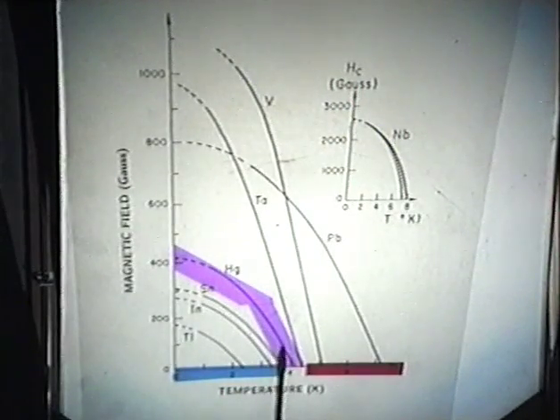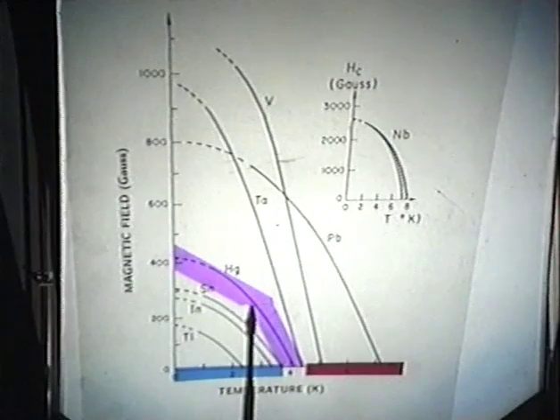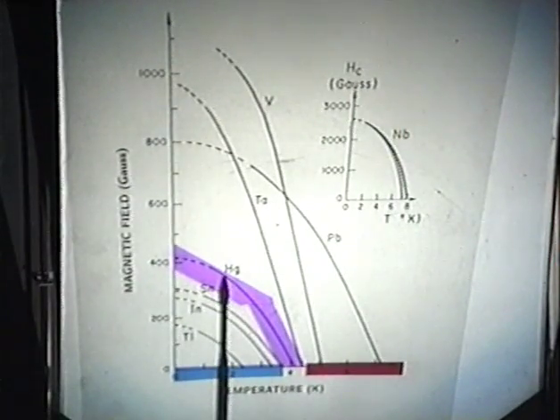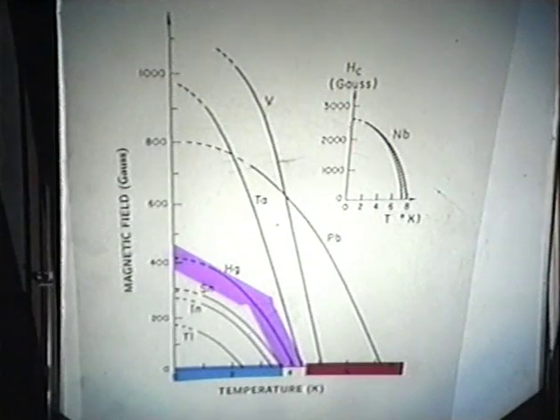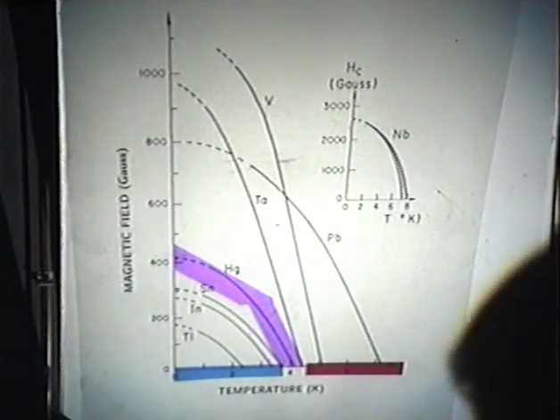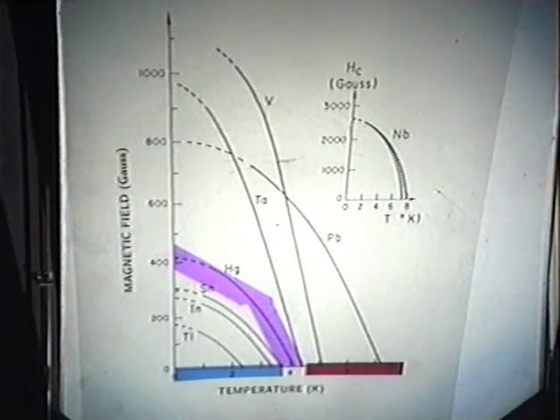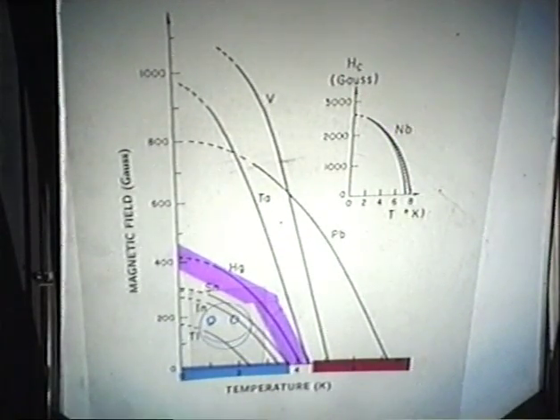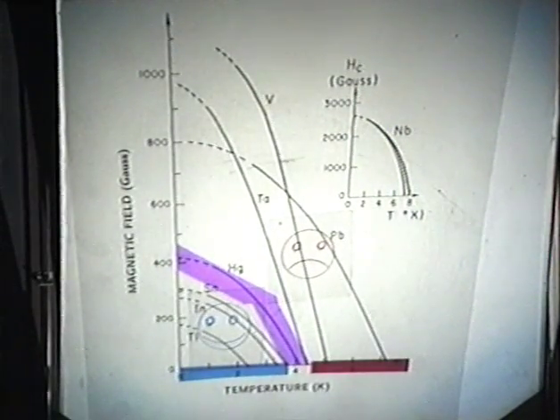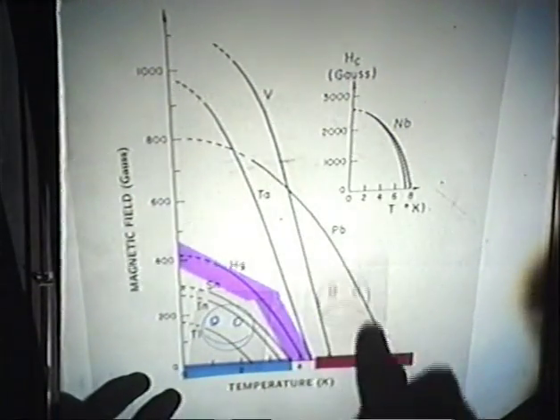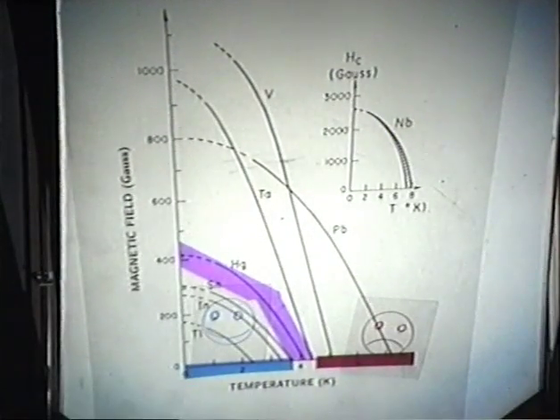And so on. You can keep raising the field. You keep moving up this way and then having to lower the temperature. Raise the field, lower the temperature, raise the field, lower the temperature until you reach a point even at absolute zero, extrapolated to absolute zero, above which the mercury will no longer act as a superconductor. So that region there is the good bit, and that region out there is the bad bit. Anywhere out there, up there, down there, over here, anywhere for mercury, that's bad. It's only good under there as a superconductor. Out here it's perfectly normal.